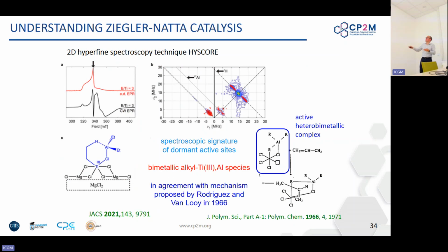And if you do HYSCORE techniques, so these are 2D techniques where you try to see what is in the vicinity of this titanium 3, you end up with hydrogen, aluminum type of interferences. So you can determine something with the help of DFT that resembles this type of octahedral titanium 3 dormant site, because if you look closely, you realize that on this site, there is no empty coordination site. No monomer can access that. You need decoordination of one of the chlorines to turn it into something that will become a polymerization active site. And this is possible with just adding ethylene, okay?